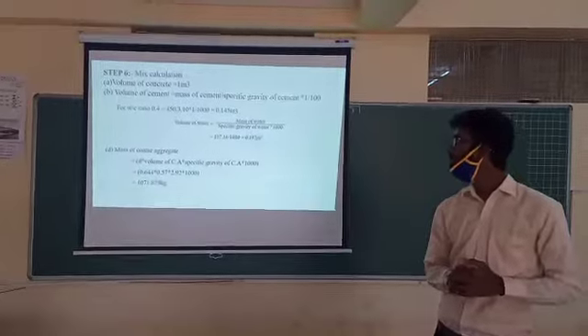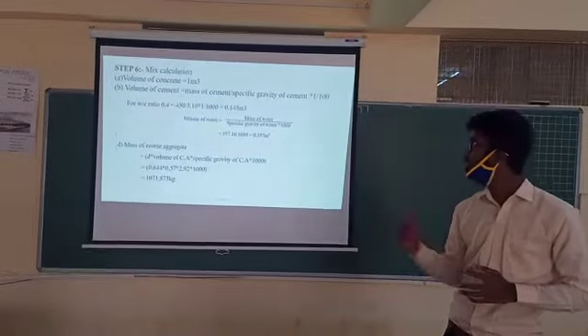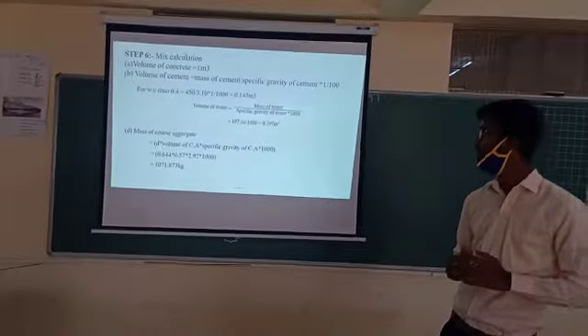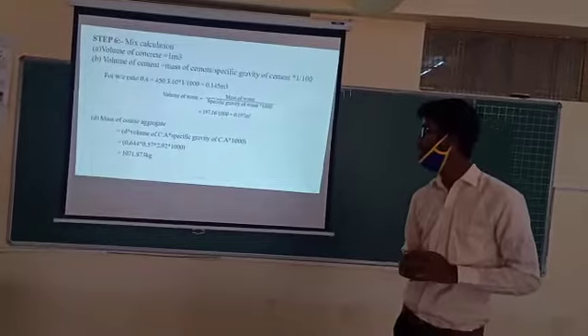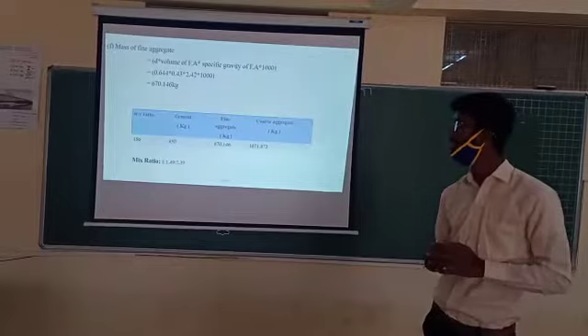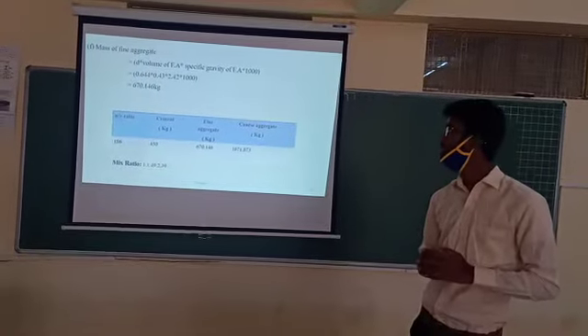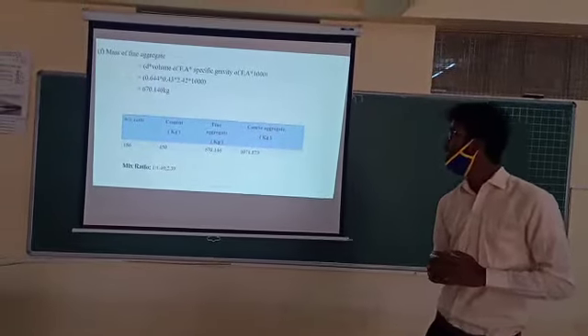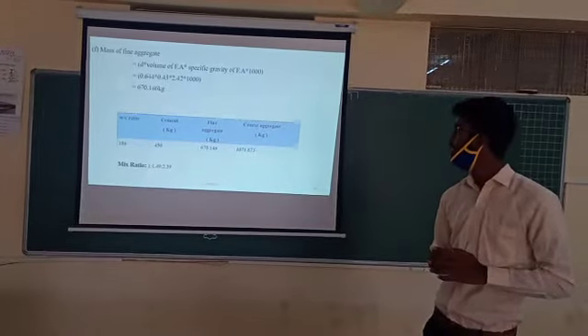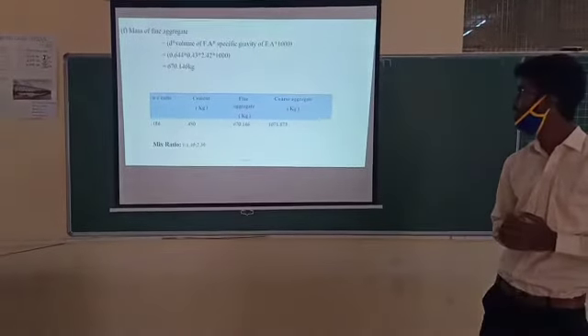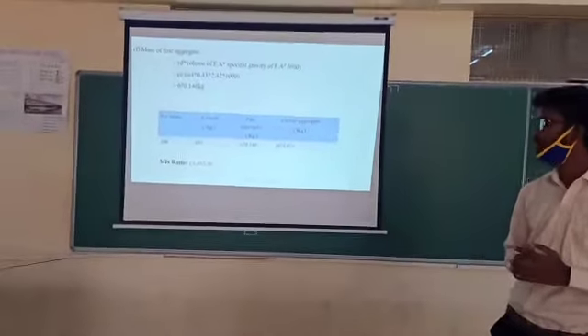And for volume of 1 meter cube concrete, volume of cement is 0.145 meter cube and volume of water is 0.197 meter cube. Mass of coarse aggregate is 1071.873 kg and the mass of fine aggregate is 670.146 kg. Water is 186, cement 450 kg, fine aggregate is 670.146 kg, coarse aggregate is 1071.873 kg. We got a mix ratio of 1:1.49:2.39.